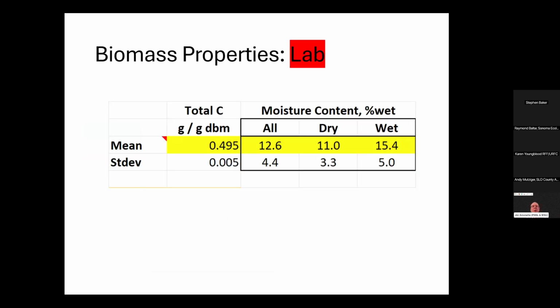Now, shifting over to the lab, we tried to dry, we had the dry stuff, and then we tried to wet it, and there was very little difference between the two. I mean, significantly, there's no difference, but the average moisture content for all those treatments in the lab was about 13% moisture, which is pretty darn dry, actually. But that was a hot summer in Missoula, what can we say?